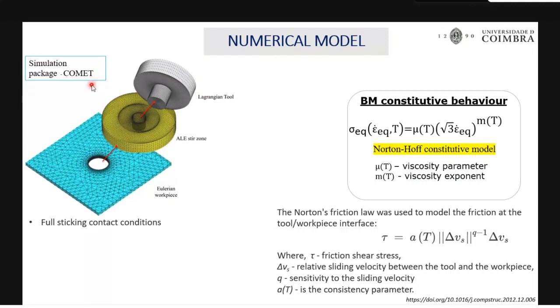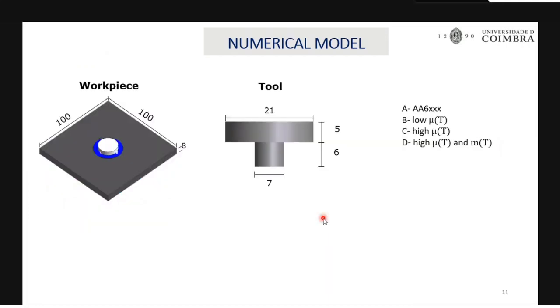This is software developed by a university from Barcelona, Spain, and we use that software for simulating this. A full sticking condition is used. I used this condition based on my previous trials, which showed good agreement with the experimental condition, so I stick to that. The Norton-Hoff constitutive model is used to model the material behavior, and the friction condition is based upon the Norton friction law.